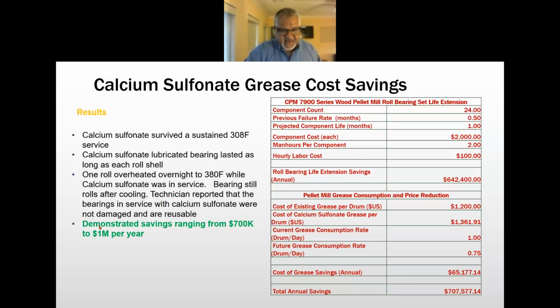So let me show you how we demonstrated savings ranging from $700,000 to $1 million per year just by using a more expensive calcium sulfonate grease versus the synthetic lithium complex grease. There are 12 presses, 24 bearings, previous failure rate, 2 weeks. What if we just allow your bearings to last for a month? Each bearing costs $2,000. Annually, I could save them just on the cost of bearings, $650,000 annually. I also suggest that you reduce the amount of grease that you consume.